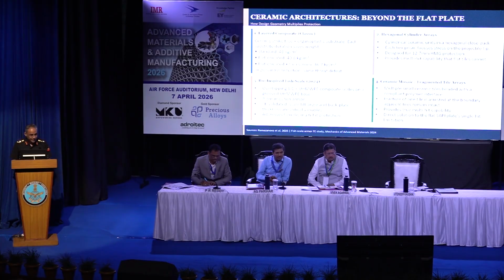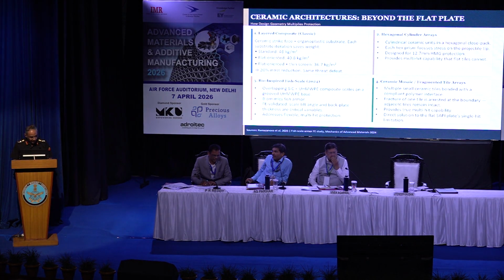The baseline is the layered composite ceramic strike face, organoplastic backing, RHA sandwich, and it is 46 kg per square meter. And the baseline drops to 36.7 kg per square meter when we put a screen. This is the modification we are giving to the simple ceramic plate, which means a 20% weight reduction for identical threat defeat. 20% lighter means 20% more mobility, 20% more time before musculoskeletal injury that will degrade the combat effectiveness.